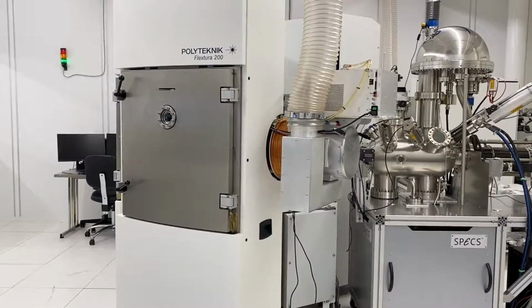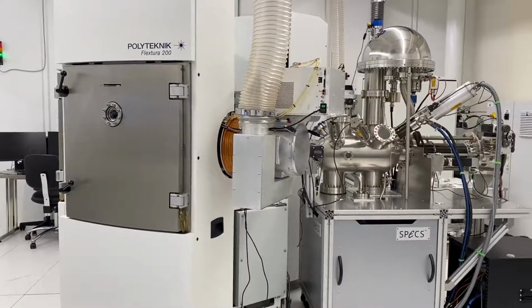The second chamber is a bit more of a special chamber. It's specifically designed for the University of Oslo. It's quite unique. It has a remote plasma generator, meaning the plasma is generated externally with an RF source, injected into the chamber and held in place by electromagnets. What this does is that it decouples the plasma density, which allows you to do quite high reactivity of the deposition, but you don't necessarily have to do such a high power on the target.